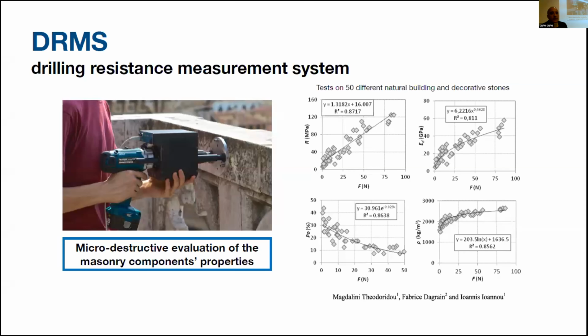Anyway, we need some mechanical information in any case, because also if we use a micro-mechanical model for brick and a micro-mechanical model for mortar, we need some experimental information, but we can use not so destructive tests. For example, we can use this drilling resistance measurement system. We have to use this drill, and there are some correlation curves between the force that you use to make the hole in the material, and some mechanical properties.